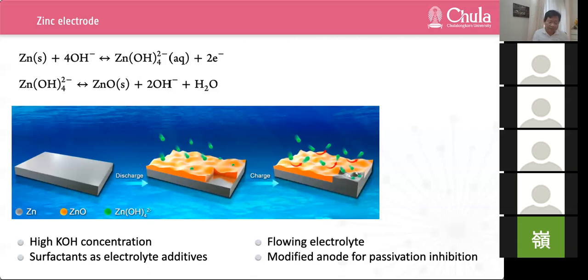By adding the appropriate amount of surfactants to the electrolyte can cause the passivation layer to become loose by preventing zinc oxide precipitation on the active zinc surface, which reduce the influence of the passivation layer on diffusion ability of the zinc ions generated by the discharge reaction diffusing into the electrolyte, and reduce the diffusion resistance of the passivation layer on discharge products. The frequently used surfactant in zinc air battery can be divided into 3 categories.